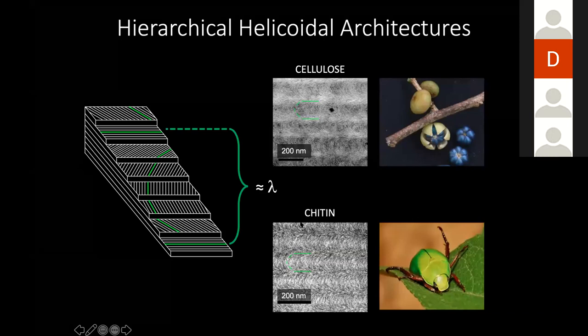For people that are not really familiar with this helicoidal architecture, when you take a cross section with an electron microscope and you start to see this arc pattern, it is called the Bouligand pattern, because Bouligand was the first one to observe it. These are really common motifs in nature. Our bones often have this type of architecture, because it's also good for mechanical support. When in cross section you see this arc pattern, it means that the fibers are, I try to make a scheme here on the left part of the screen, essentially twisting. And again, when the twist is comparable with the wavelength of light, you can reflect coloration.